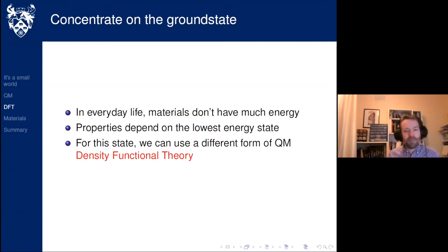The properties of a material depend almost entirely on this lowest energy state. And if all we're interested in is computing the lowest energy state, not all the states, we can actually use a different form of quantum mechanics. And that different form of quantum mechanics is known as density functional theory.